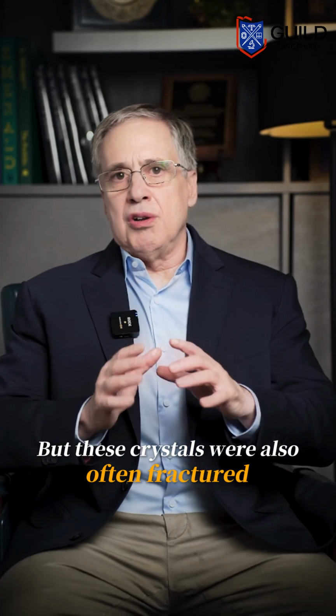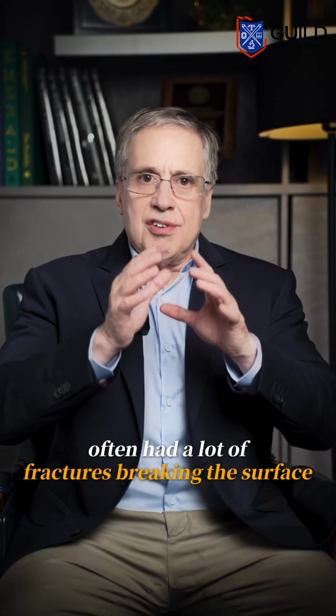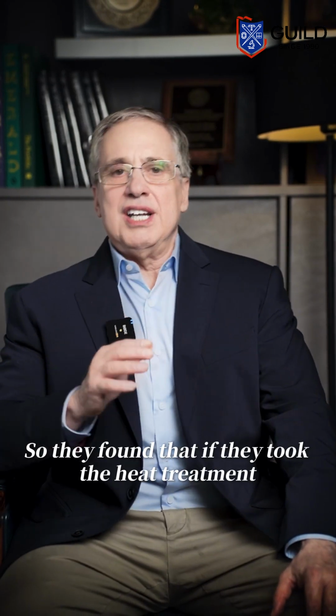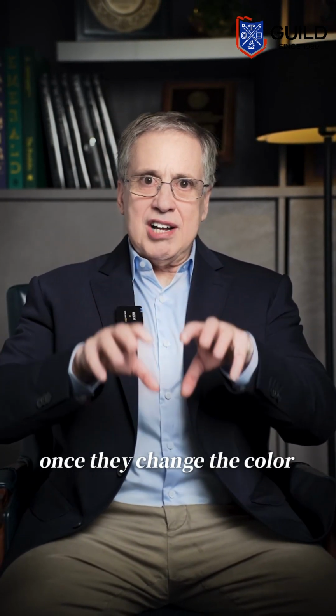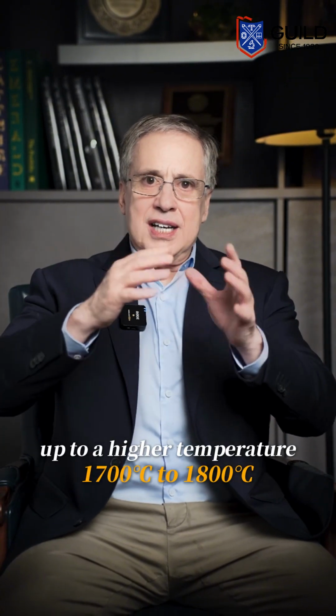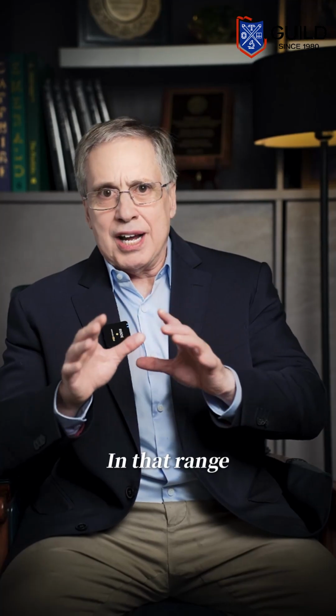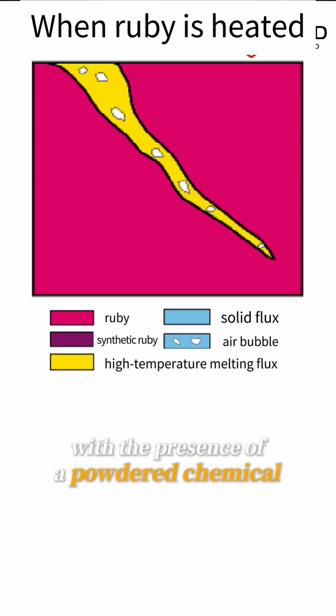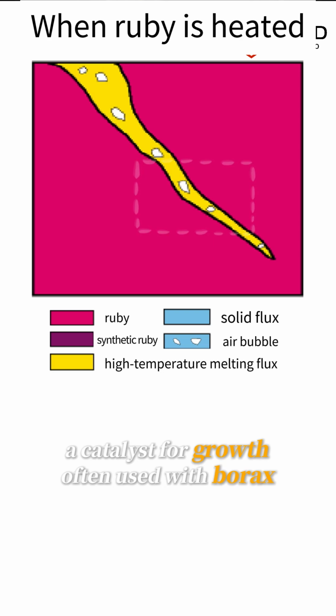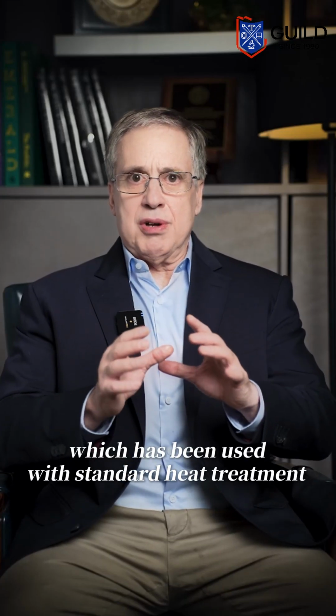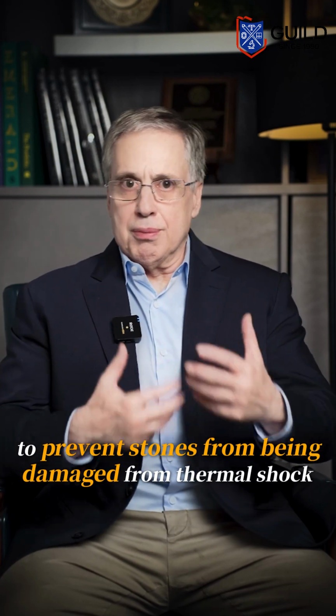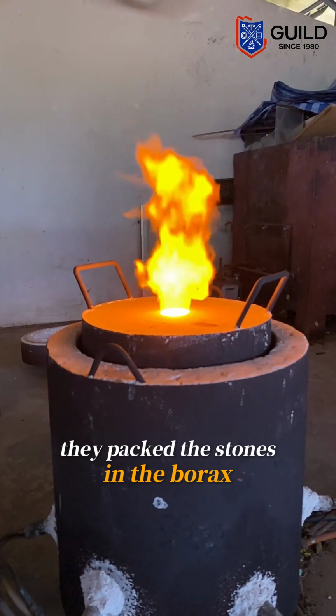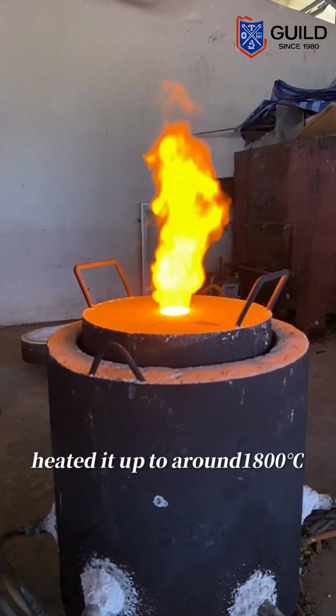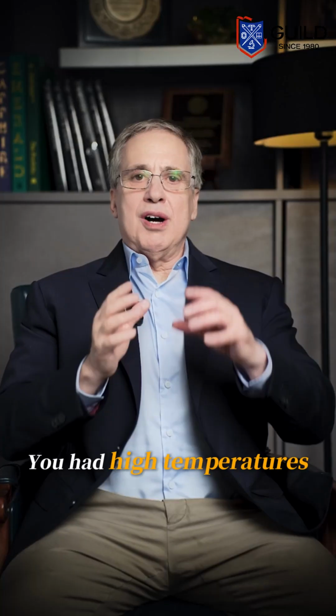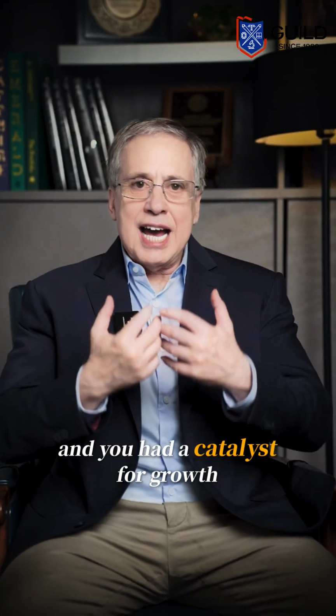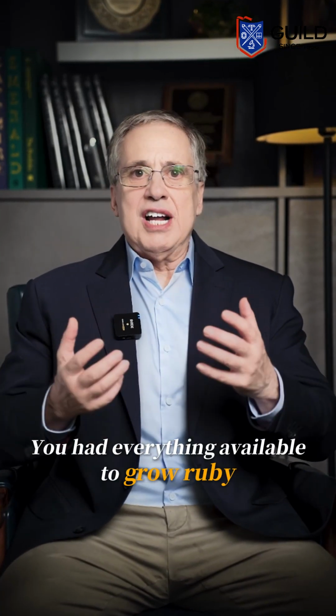But these crystals were also often fractured, often had a lot of fractures breaking the surface. So they found that once they changed the color up to a higher temperature, 1700 to 1800 degrees centigrade, in the presence of a powdered chemical, a catalyst for growth, often borax, which has been used with standard heat treatment to prevent stones from being damaged from thermal shock. In this case, they packed the stones in the borax and heated it up to around 1800 degrees centigrade. What happened? Well, you had high temperatures and you had a catalyst for growth. You had everything available to grow ruby.